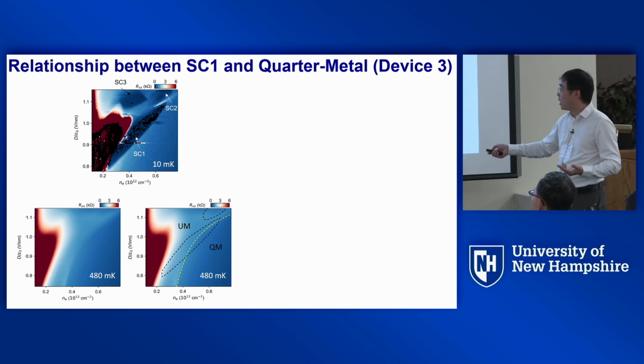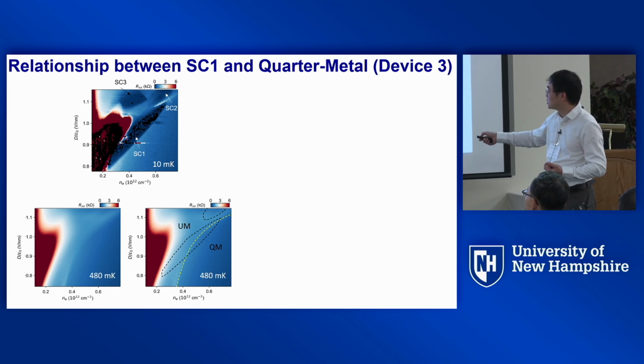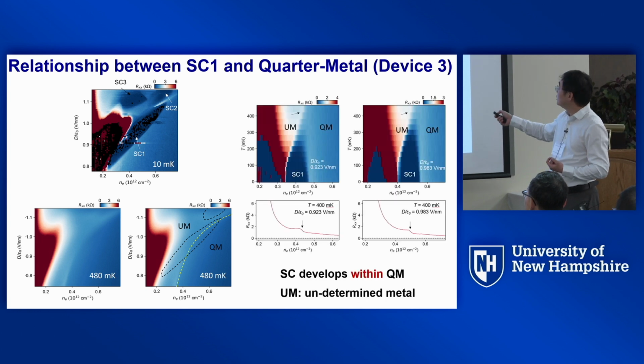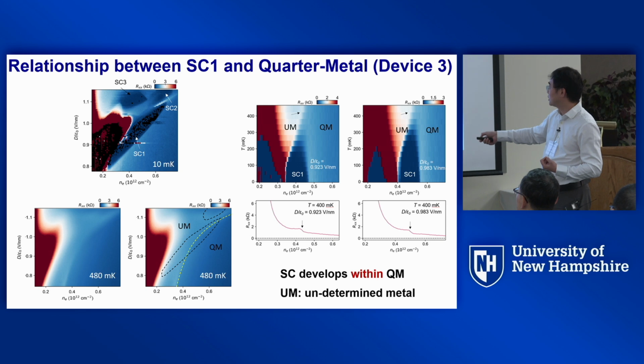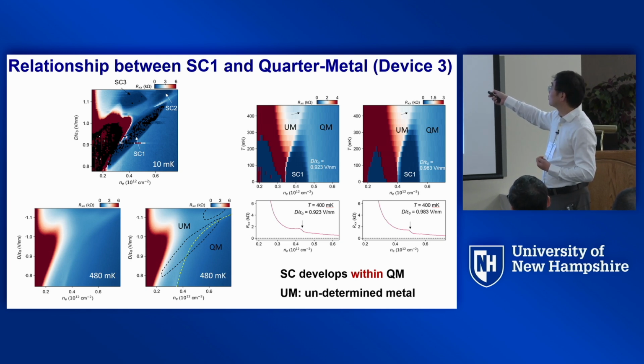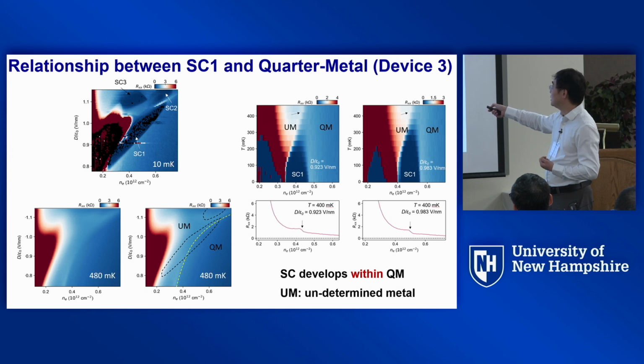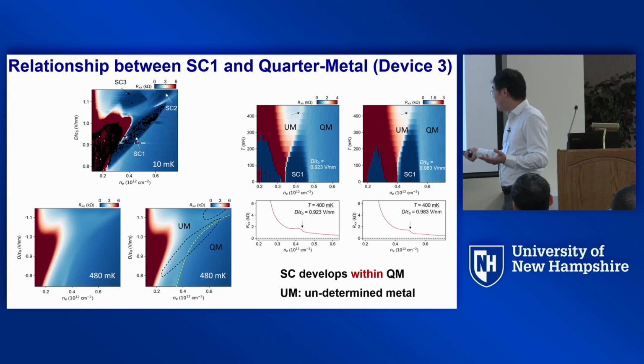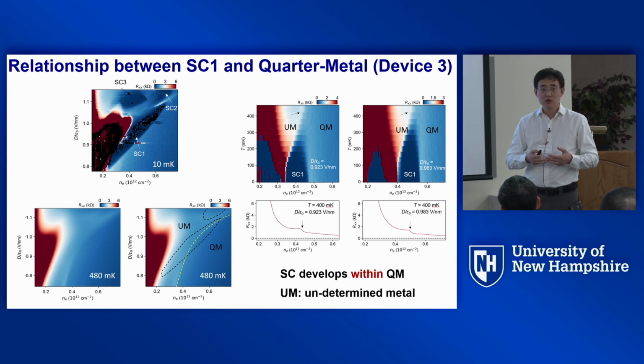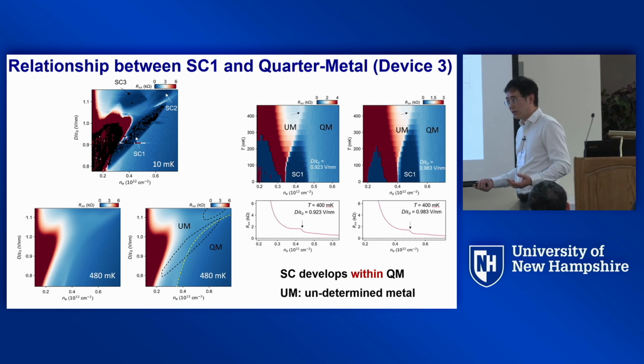But that's actually not true, because this boundary, this yellow dashed line here, actually will shift as a function of temperature. If you do a line cut at a constant displacement field, for example, here or here, you can tell this side is a quarter metal. This kink here corresponds to the yellow dashed line. At high temperature, it's at a relatively high charge density, while when you cool it down, it actually shifts to lower charge density. And then SC1 develops to the right of this boundary. So the quarter metal somehow is extending to lower charge density, and superconductivity is only residing to the right of it at both line cuts. Okay? So this gives us more confidence that the parent state of SC1, at least, should be thought of as a spin and valley polarized quarter metal.